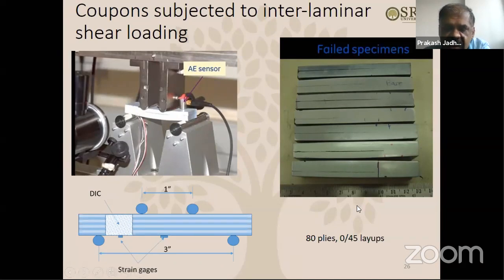As far as the specimens are concerned, you can see there are 80 plies thick specimens, mostly 0/45 plies. You can see the cracks were initiated at this location and then propagated to the other end. You can clearly see all these delamination cracks. They initiated at this ply drop location and then propagated.